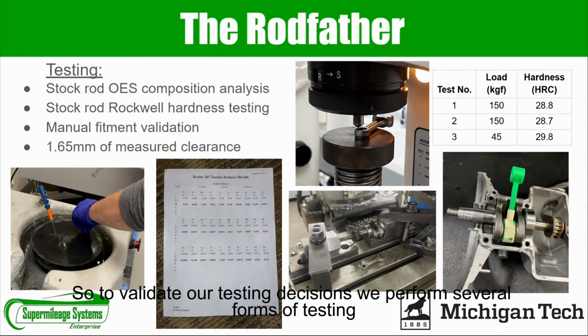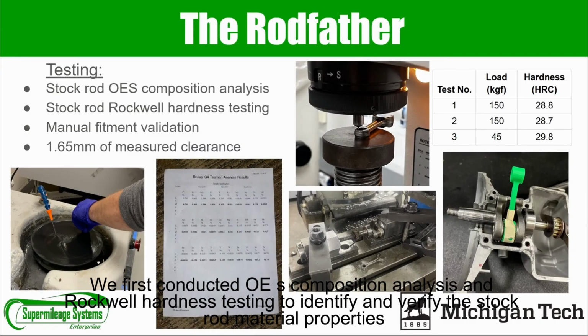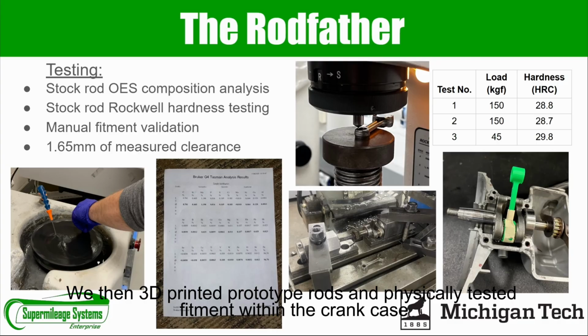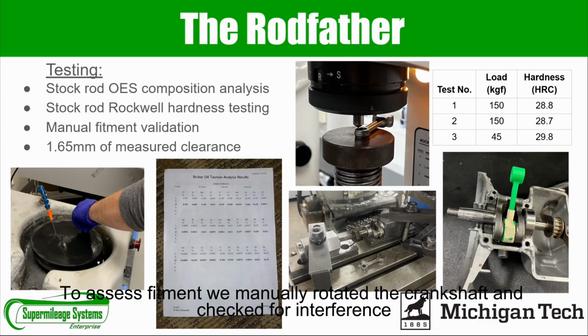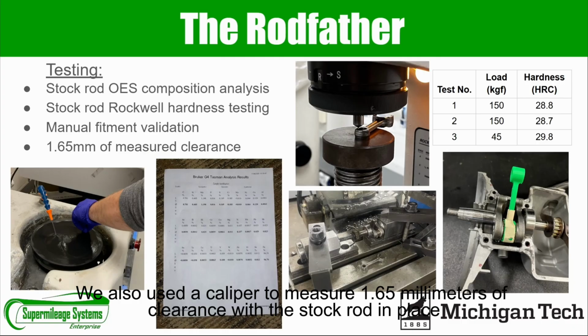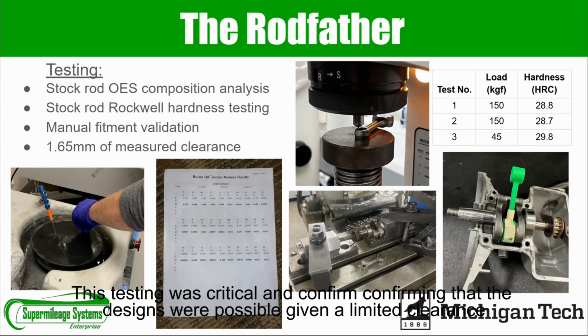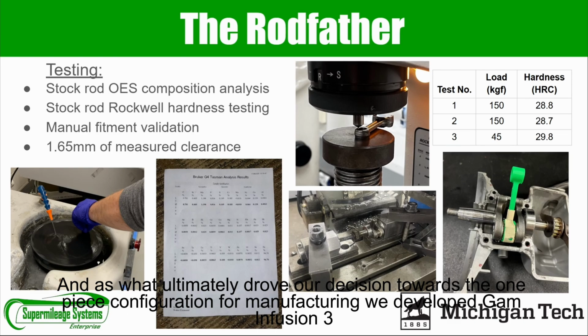So to validate our design decisions, we performed several forms of testing. We first conducted OES composition analysis and Rockwell hardness testing to identify and verify the stock rod material properties. We then 3D printed prototype rods and physically tested fitment within the crankcase. To assess fitment, we manually rotated the crankshaft and checked for interference. We also used a caliper to measure 1.65 millimeters of clearance with the stock rod in place. This testing was critical in confirming that the designs were possible given the limited clearance, and is what ultimately drove our decision towards the one-piece configuration.